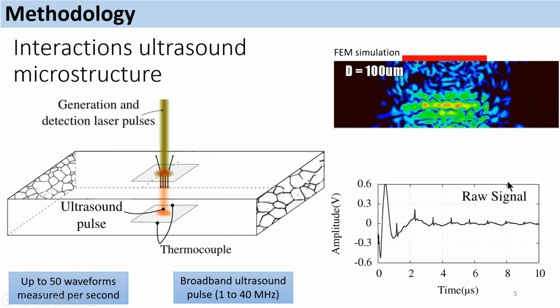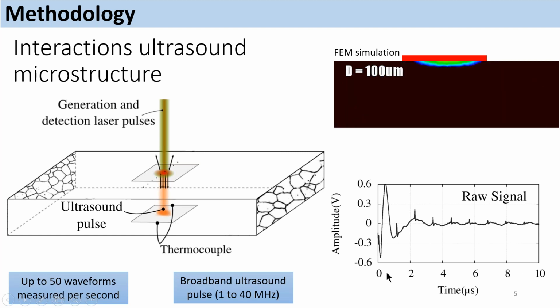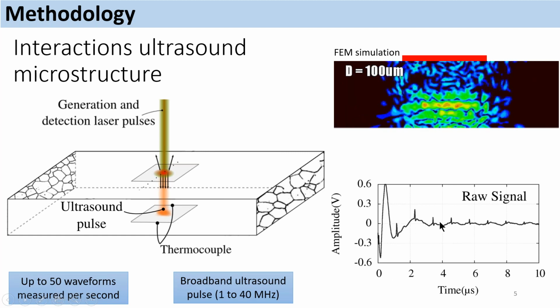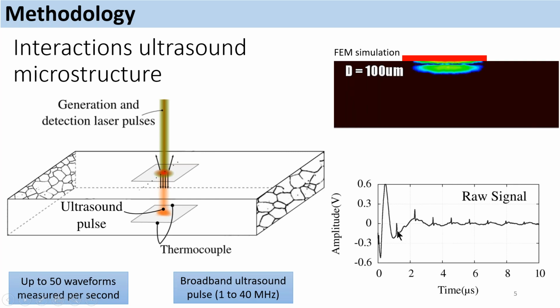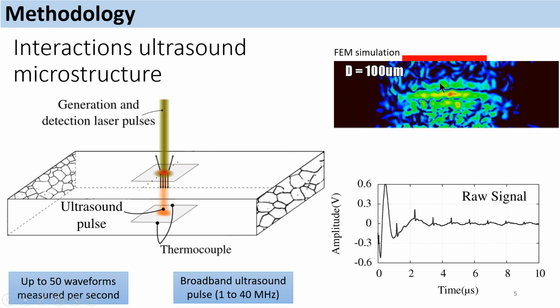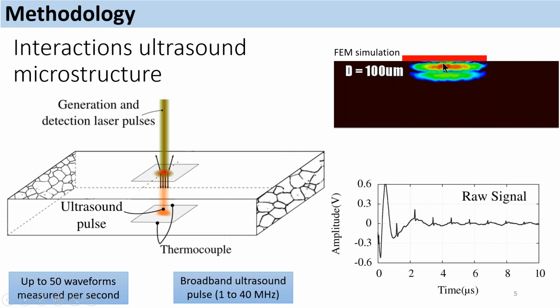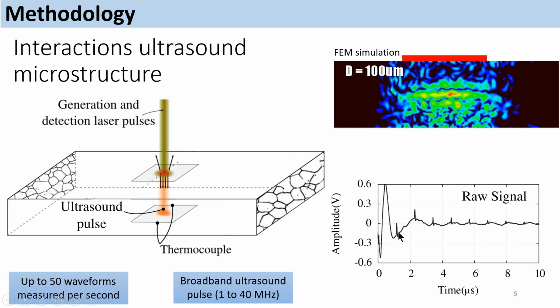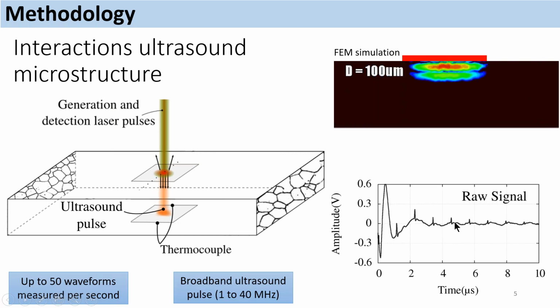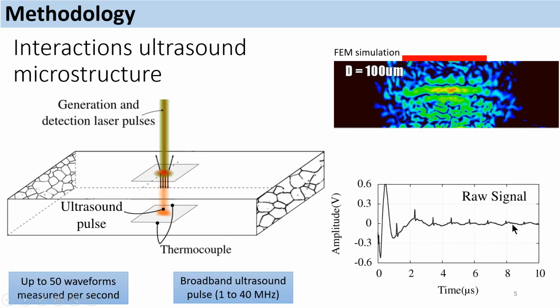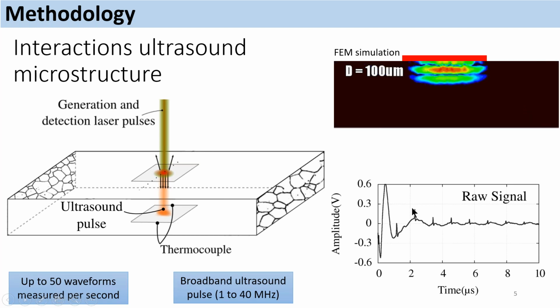So those waveforms can be visualized here, and those peaks that you see on the waveform correspond to the moment in which the pulse comes back at the generated surface. So you can see that we can measure many times the pulse coming back at the generation surface.